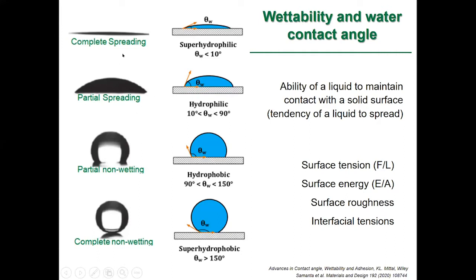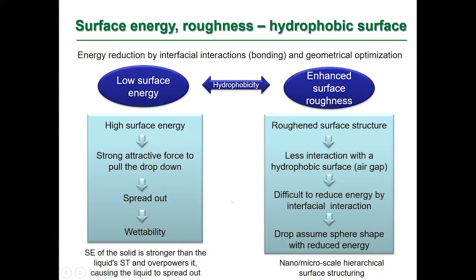So you can see the typical case, complete spreading. It is called superhydrophilic. Partial spreading is hydrophilic, with a contact angle between 10 and 90, and then hydrophobic. And when we have a high contact angle greater than 150 degrees, it is called superhydrophobic. For an already hydrophobic surface to become superhydrophobic, the two important parameters are low surface energy and enhanced surface roughness.